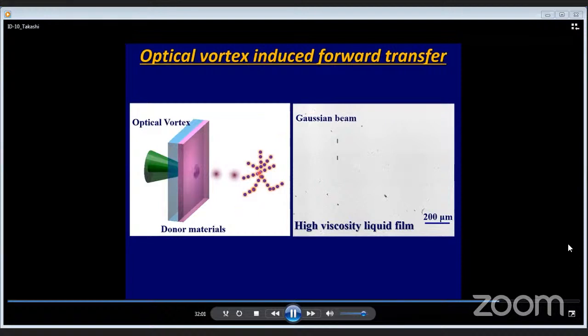I would like to show you one interesting movie. We prepared a high viscous liquid film, with a viscosity of 4 pascal second, which corresponds to honey, like mayonnaise or something, very high viscosity. We pump such a high viscosity liquid with a conventional Gaussian beam, wavelength 532 nanometer. The donor broke into many fragments right away. Of course, we cannot control the flight of the fragments at all.